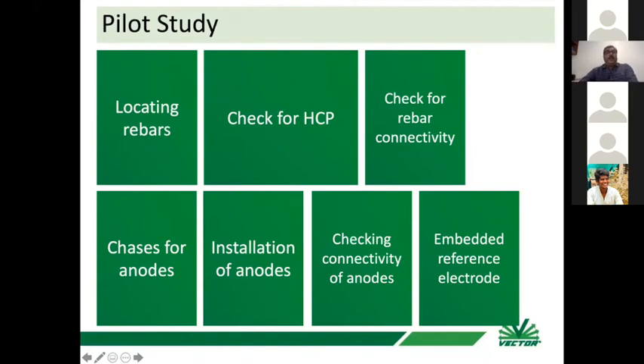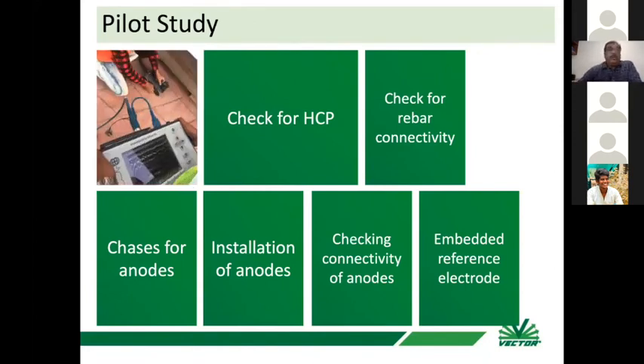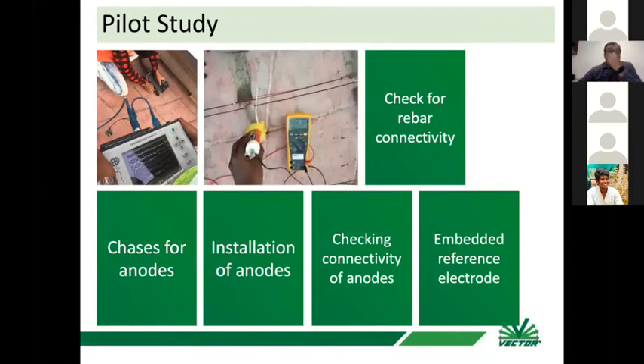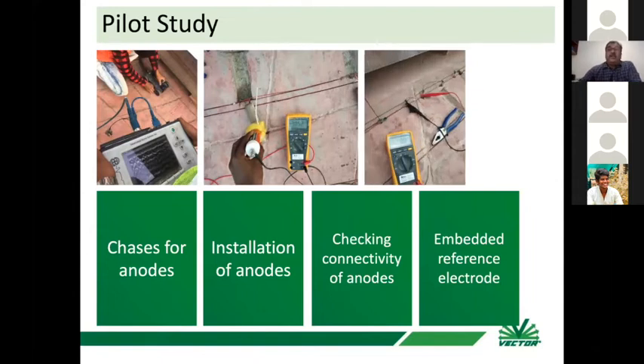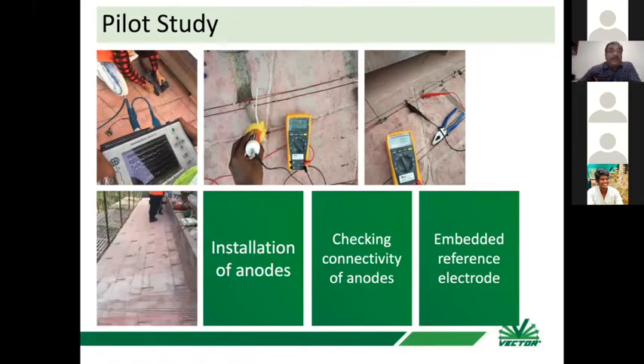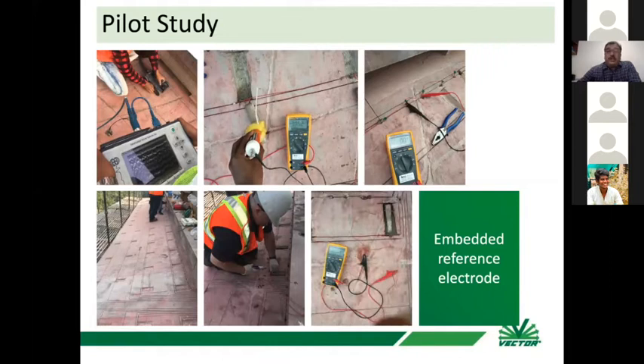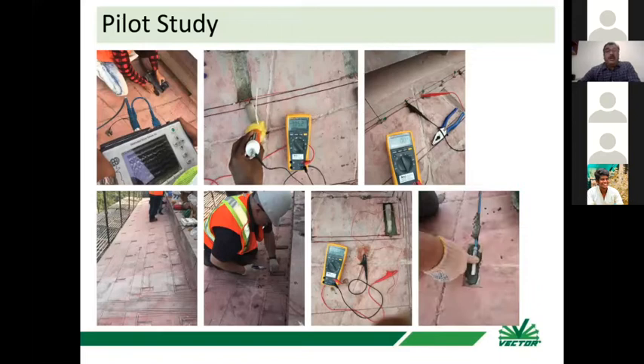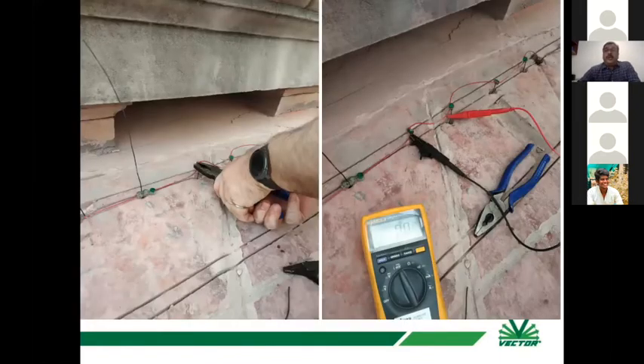Like if I show you various photographs, first of all, we located the rebar using GPR. Then we checked the half cell potential regularly in a grid pattern. Then we checked the connectivity of the rebar. All rebar were not connected. So we introduced a special rebar connector at the top, and then we connected all the rebar with a wire, and they were embedded, and we checked connectivity of all the rebar, like every 5 centimeters, 7 centimeters. Then we made a small chase for installing the anode, and the anodes were installed. Again, the connectivity of the anode was checked, whether anodes are connected properly. And then we also installed one embedded reference electrode, so that we don't need to go there using a surface electrode for measuring half cell potential. And these are some photographs of checking the connectivities.